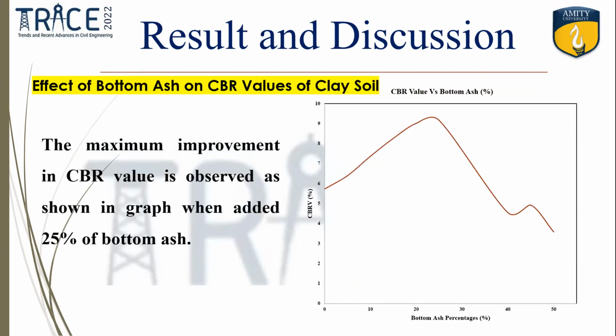Effect of bottom ash on the CBR value of clay soil: as shown in the figure, the maximum improvement in the CBR value is observed as shown in the graph. When 25% bottom ash was added, we got the optimum content of bottom ash.